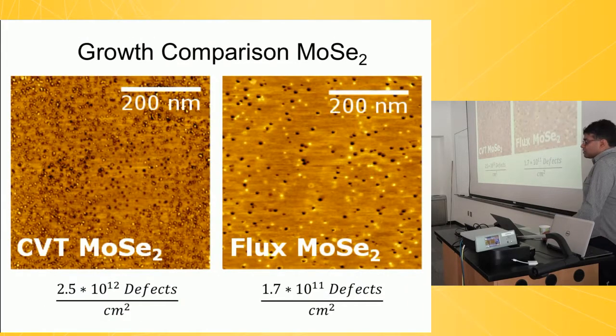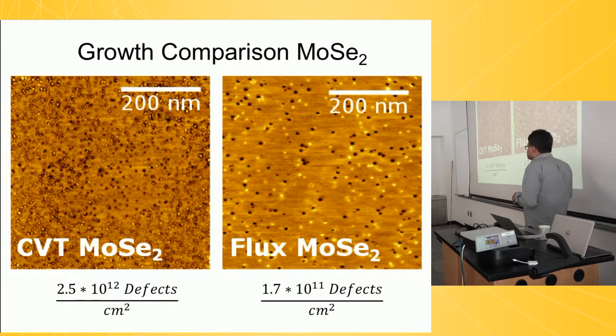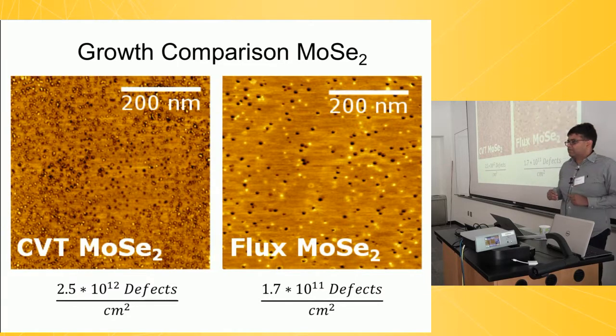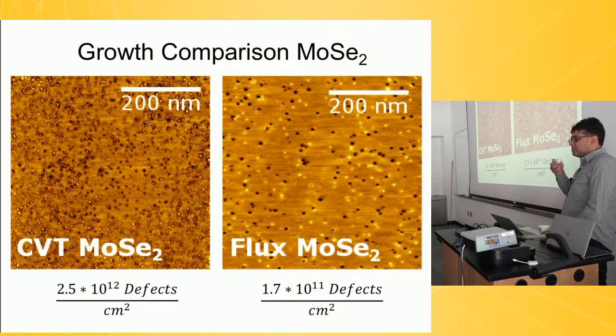Good. So let me get straight to the data. This is molybdenum diselenide, and we've studied a few different versions of the TMDs. On the left here is a CVT crystal grown by chemical vapor transport. On the right is a flux crystal. And these are cleaved surfaces. So if I had no defects, this surface would be absolutely flat. But indeed, you see that it's not flat. You see those little points that are defects. And as I'll show you in just a second, each of these points is one individual atomic defect.